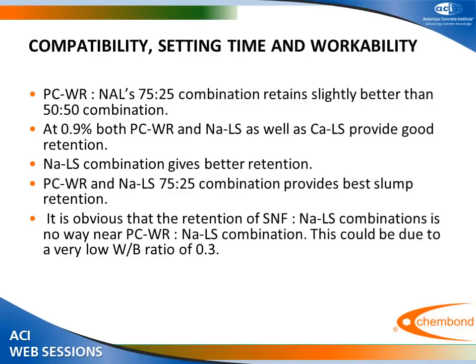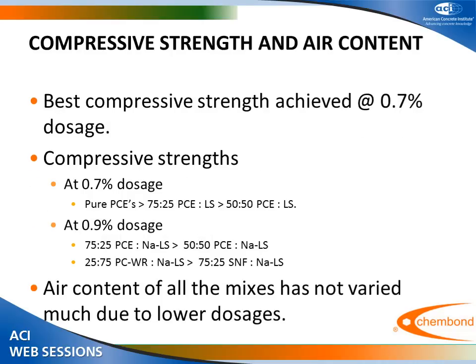And it is obvious that the sodium lignosulfonate and SNF combinations are nowhere near the PCWR and NALS combinations, and this could be because of the very low water cement ratio which was used, 0.3. Now, for compressive strengths, the best compressive strengths were achieved at 0.7%, which is obvious. At 0.7% dosages, pure PCEs, followed by 75-25 PCE and ligno, and 50-50 PCE combination. This is how the compressive strengths have come.